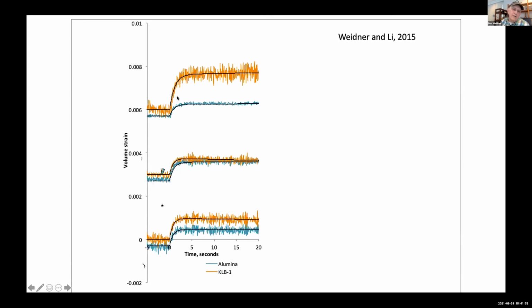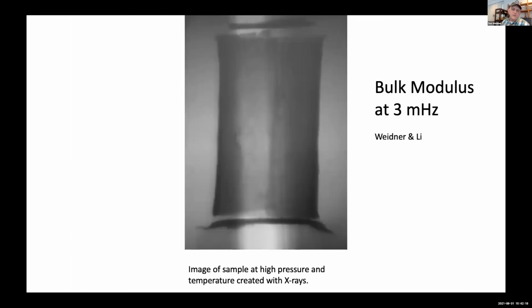There's this little funny curvature at the beginning, always in these. Whether you go up or down, it's shaped like this. And again, that's the thermal diffusivity controlling how fast the sample heats up. So we concluded, again, the sample heats in like 1.5 seconds, and that crossing the solidus significantly increases the thermal expansion. We decided to try the same thing for bulk modulus.